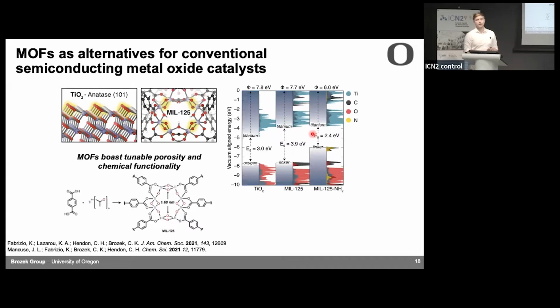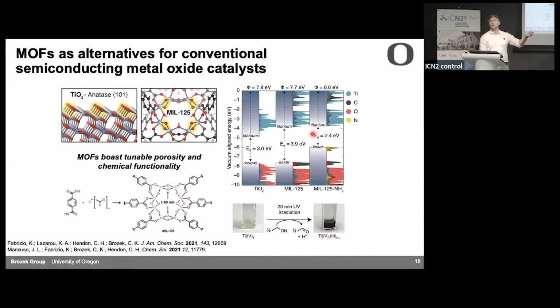The other reason that we like this MOF is because it's what really kicked off a lot of the photoredox and photocatalysis chemistry that people are doing with MOFs. The Férey group almost 20 years ago showed that you can take this MOF, irradiate it with UV light in the presence of an alcohol, and you trap highly reactive titanium 3+, and the MOF becomes this blackish purple color. So it has interesting optical properties. And we thought, if we can make this as a nanoparticle, maybe we can study its size-dependent optical properties, kind of like a quantum dot.